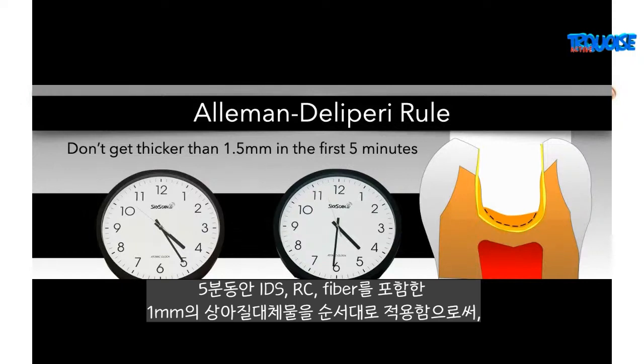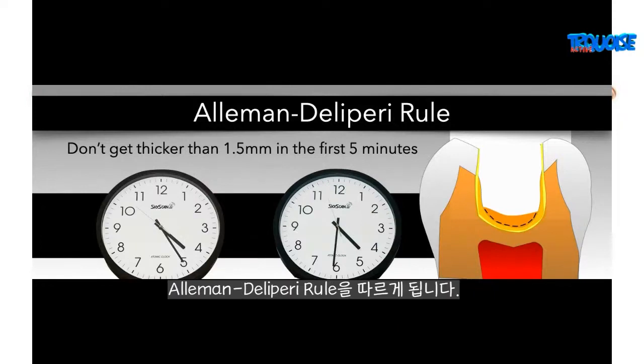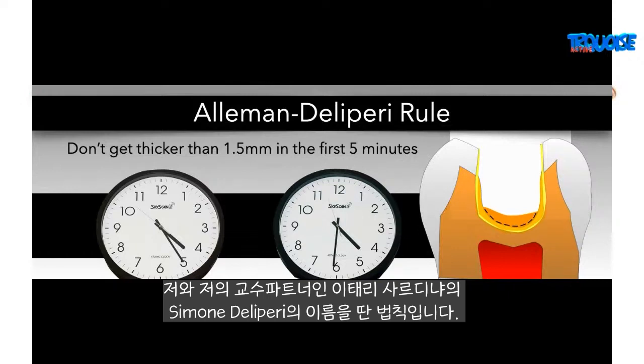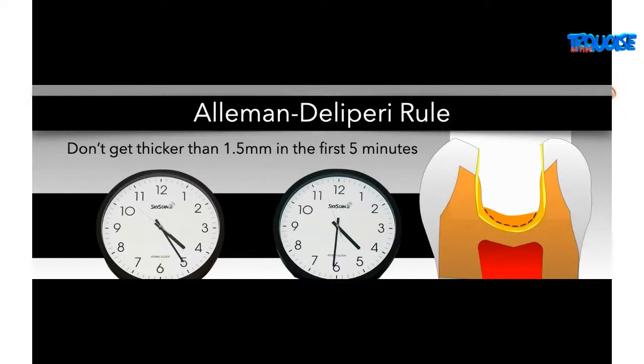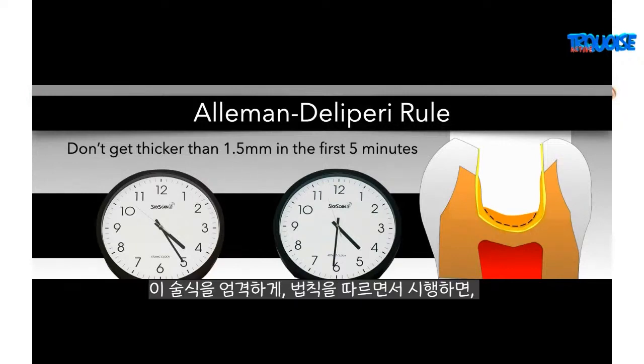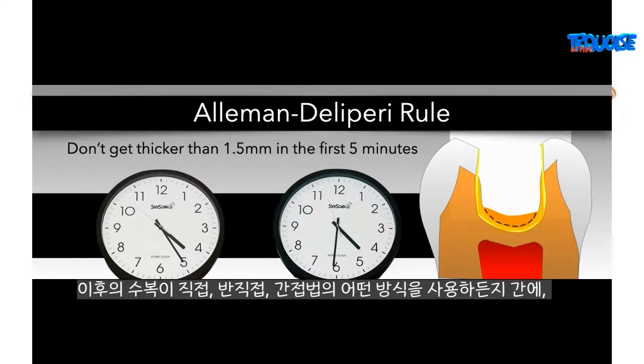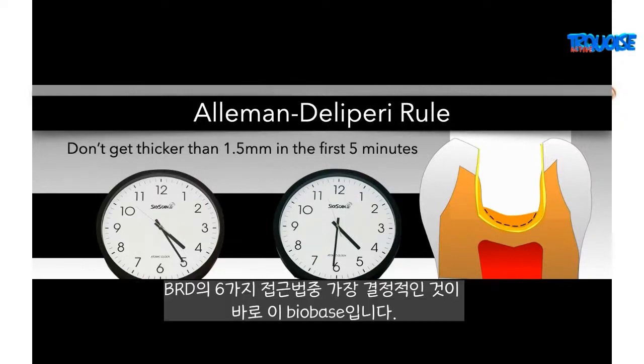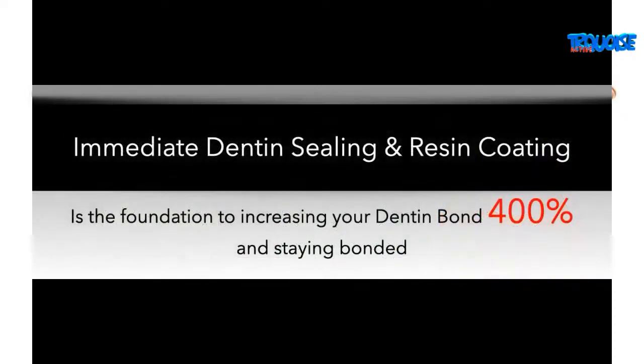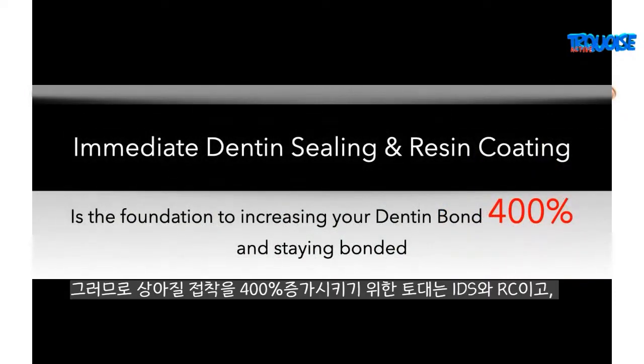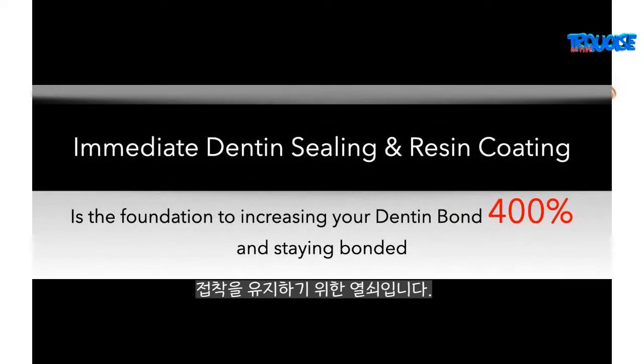So the immediate dentin sealing, the resin coating, and the 1 millimeter of dentin replacement with fiber, those placement steps in that order ensure that you don't violate the Alleman-Deliperi rule, named after obviously myself and my teaching partner for 10 years, Simone Deliperi from Sardinia, Italy. And so by doing this disciplined and not violating this, this is called a biobase, whether the remaining restoration is done direct or semi-direct or indirect. This is the biobase that is critical to the 6 lessons approach of biomimetic restorative dentistry. So immediate dentin sealing and resin coating is the foundation to increase your dentin bond 400%. And that's the key to staying bonded.